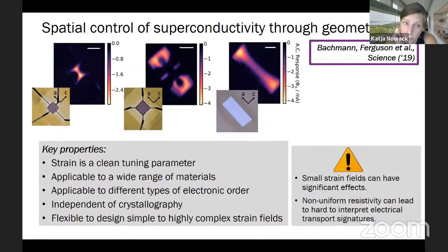Which is really fairly small. The strain fields weren't so high, but even small strain fields can, for some materials, have very significant effects. And then, of course, the whole puzzle started by assuming that the resistivity in the device would be uniform. And so here's also a cautionary tale that non-uniform resistivity in a material can lead to really hard to interpret electrical transport signatures. All right, so that was everything I wanted to tell you about these microstructures.